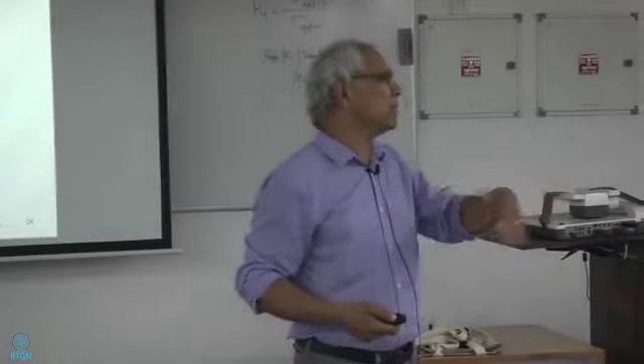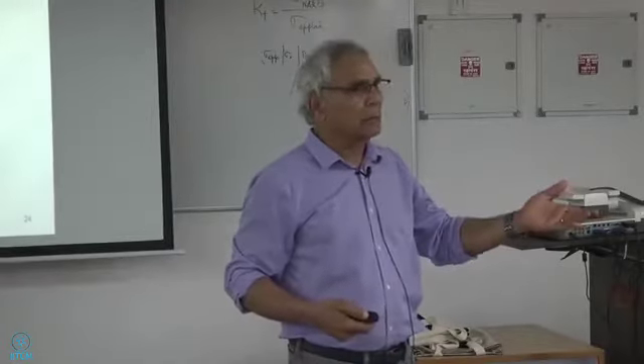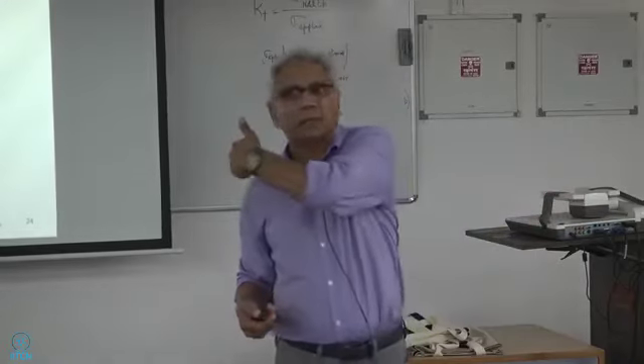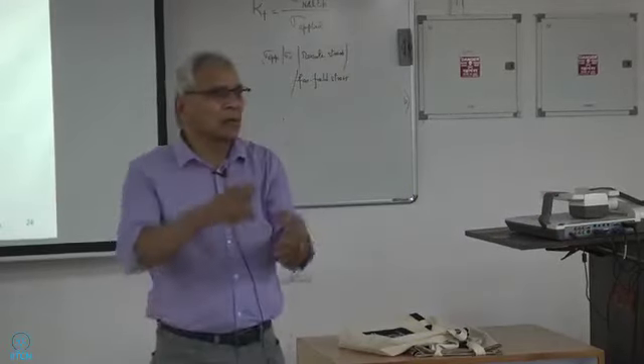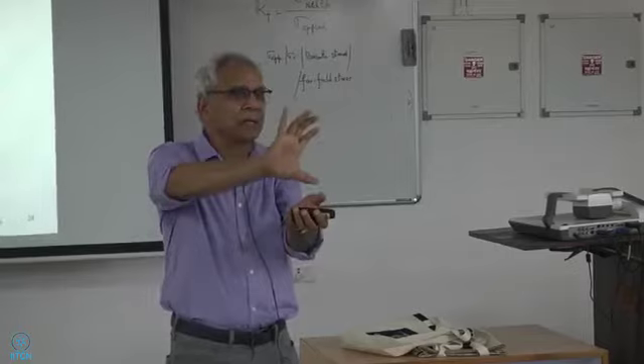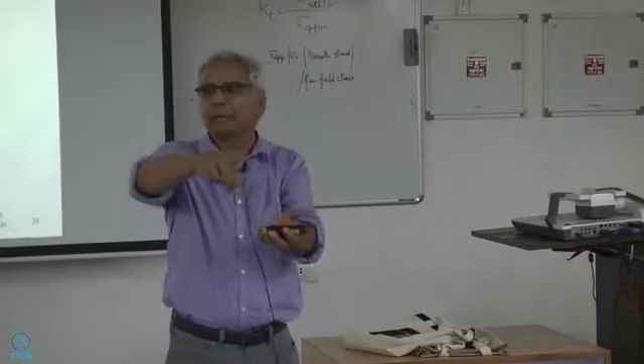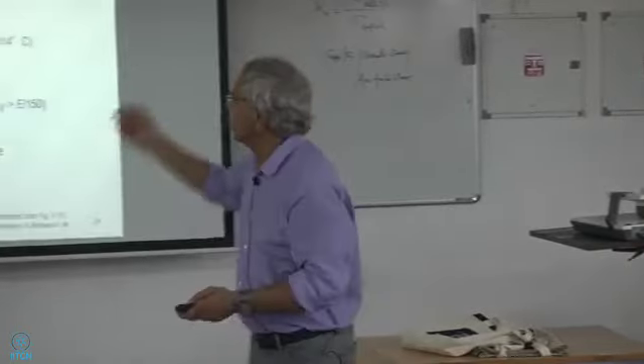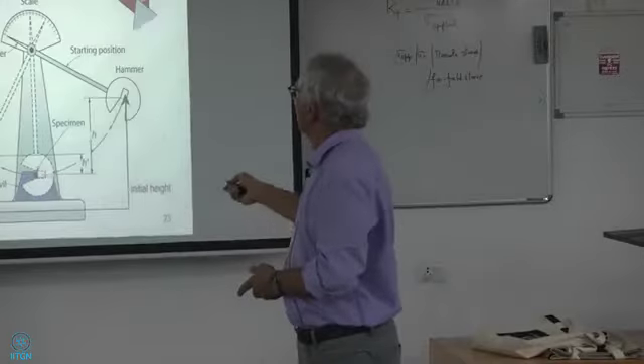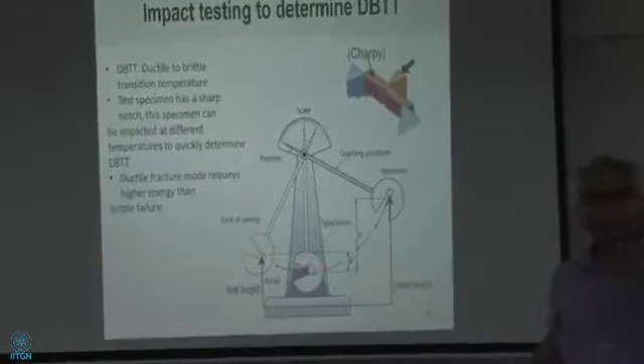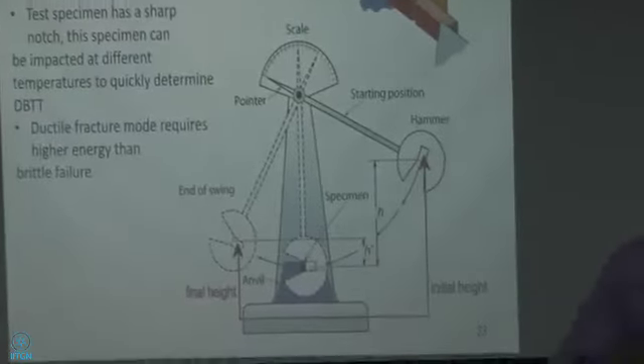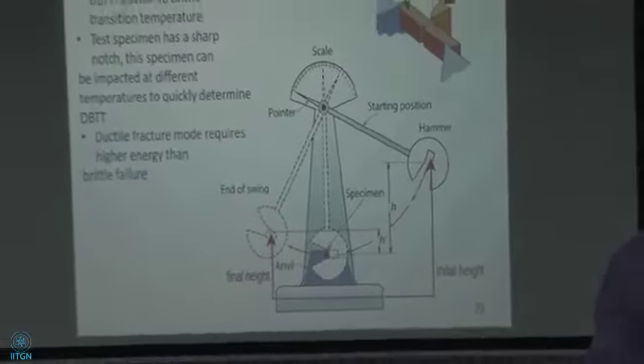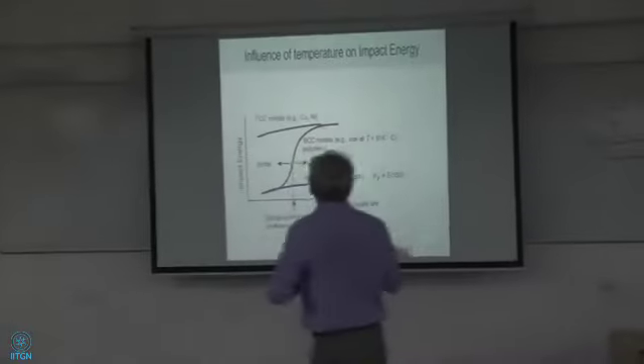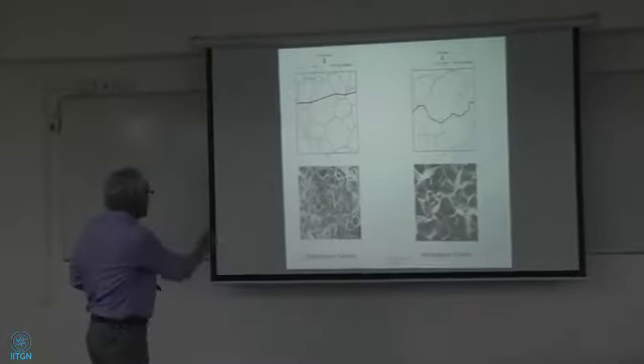Liquid helium is a little bit difficult to get. But liquid nitrogen you can get very easily from the physics department, usually. All you need is just a little bit of liquid nitrogen in a little dewar, put your sample there for 5 minutes, take it out, and put it right there. So you can at least get 5 different temperatures without any problem. And then you record your impact energies.